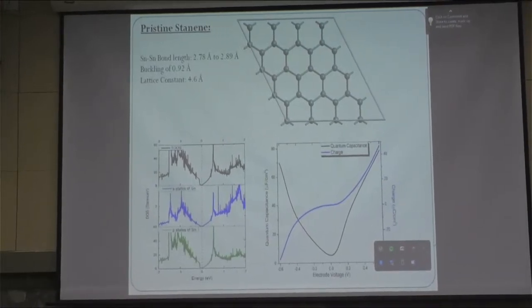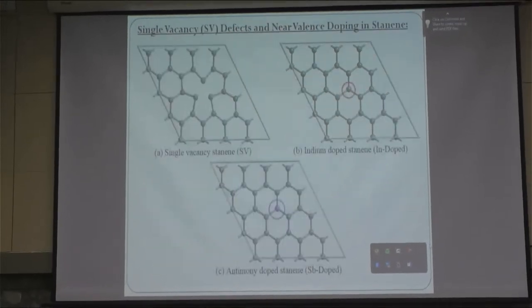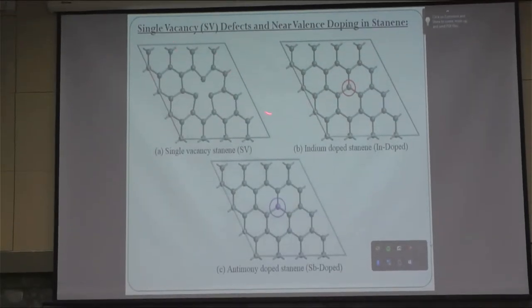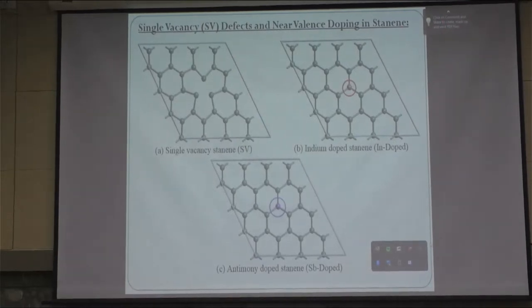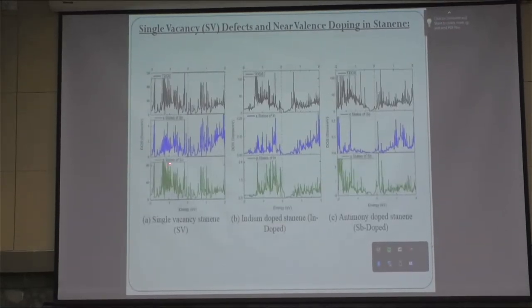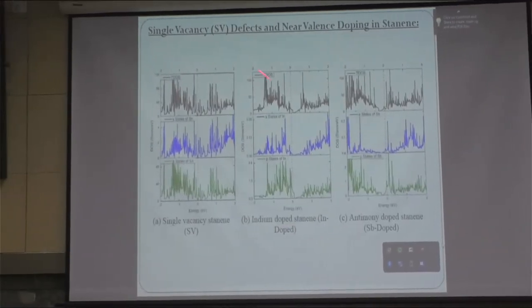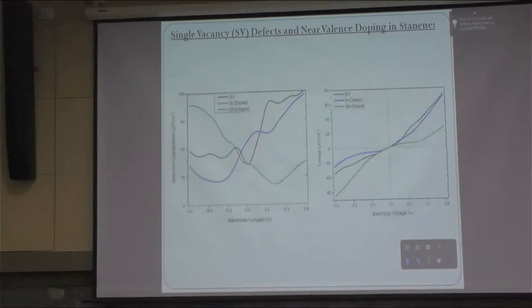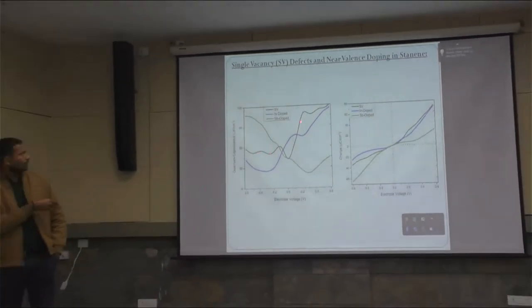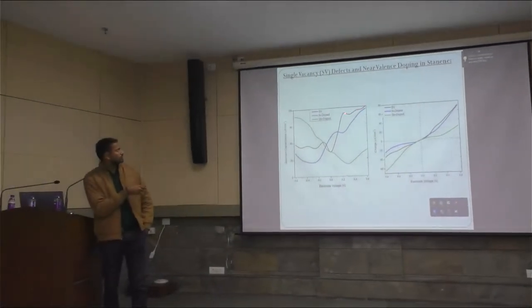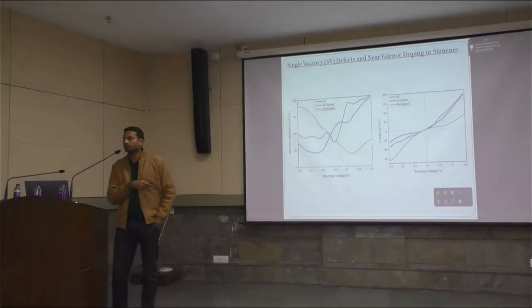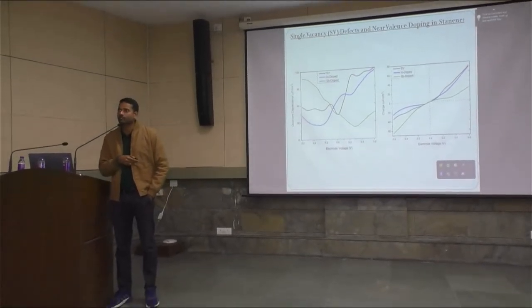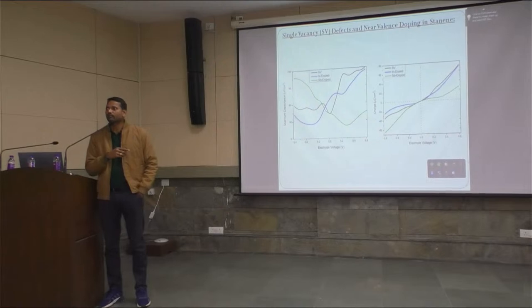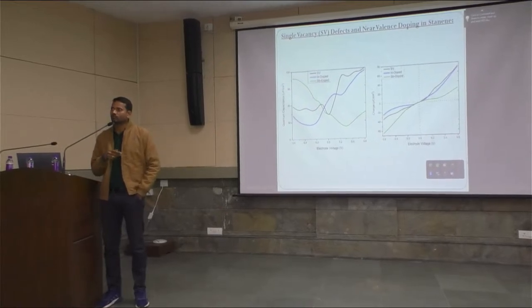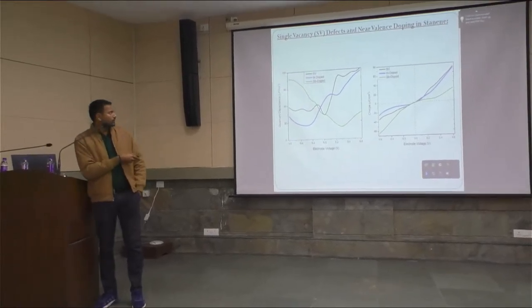To explore different ways of enhancing the quantum capacitance of stanene further, we have introduced a vacancy defect in stanene. After introducing the vacancy defect, we have found that the band gap is still zero, but the quantum capacitance increased very much. The new quantum capacitance is approximately 120 microfarad per centimeter square. Earlier it was 77. The vacancy defect increased the quantum capacitance to 120 microfarads. However,